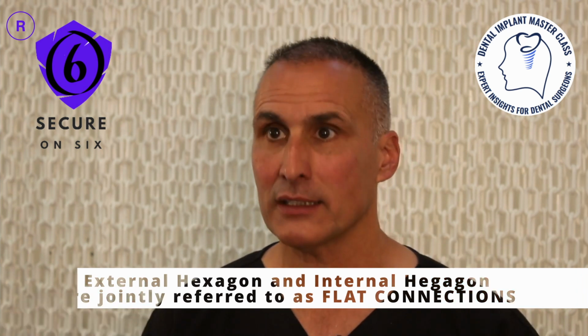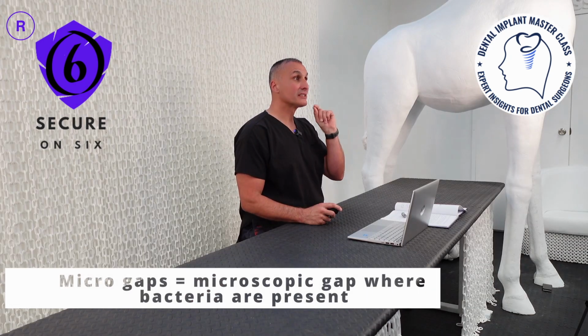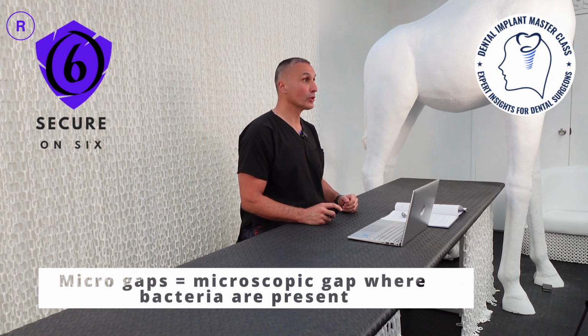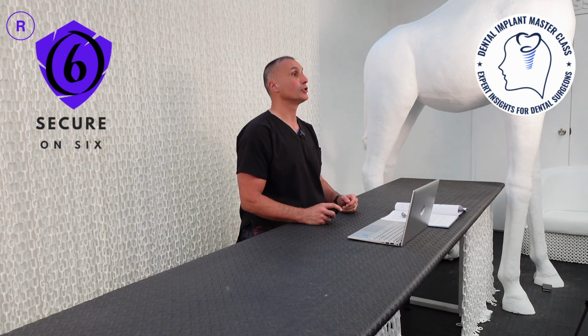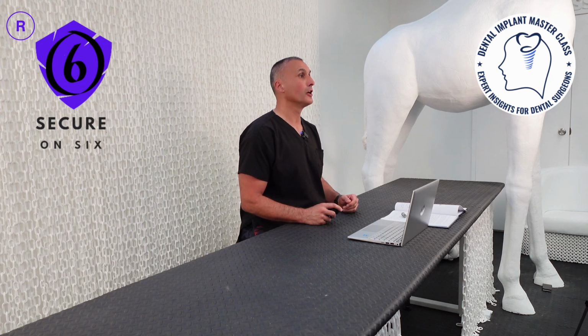Please note that different implant systems vary in structure, geometry, materials, properties, and roughness, leading to differences in maximum preload torque values. External hexagon and internal hexagon are referred to as flat connections. Flat connection systems exhibit distinct characteristics, and screws from different manufacturers have varying tensile stability. Micro gap formation, particularly in external hexagon systems, is linked to screw loosening, especially when exposed to tension forces different from the axial direction. Microspaces formed within the implant abutment interface due to micro movement can lead to bacterial colonization, mucositis, peri-implantitis, and implant loss in cases of cyclical loads. Understanding these factors is crucial in implant dentistry to address potential challenges and optimize long-term success.